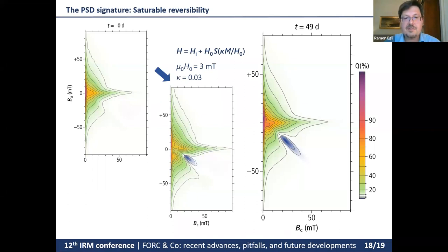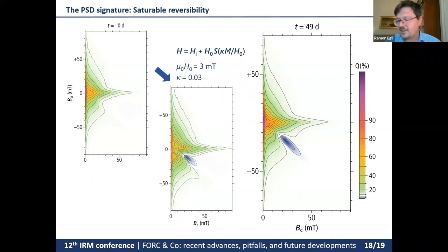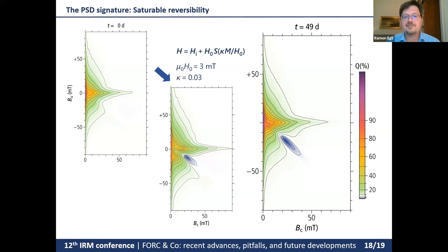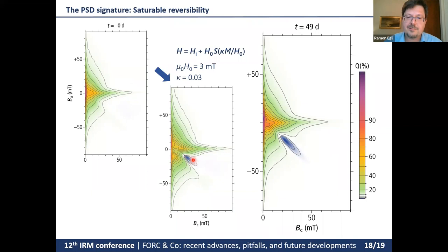An interesting thing worth studying in the future is that in this PSD range we have a sort of interaction occurring between different parts of the same particle: parts that contain well-defined magnetic states and behave rigidly with discrete transitions — possibly strongly pinned parts with defects or particle corners — and the remaining volume which behaves reversibly with a sigmoidal magnetization, interacting with the other part to produce the negative diagonal.